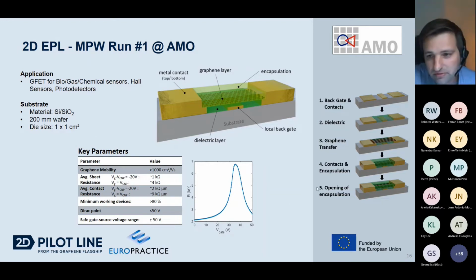The process of these devices is shown roughly in this sketch here. So first the backgate and the contacts will be deposited, then the dielectric. The graphene is then transferred before the contacts and the encapsulation will be done. And optionally, we also have the possibility to open the encapsulation on top of the graphene layer.